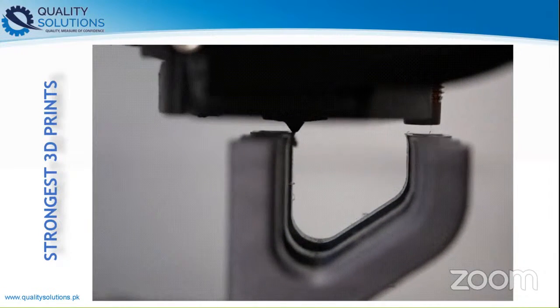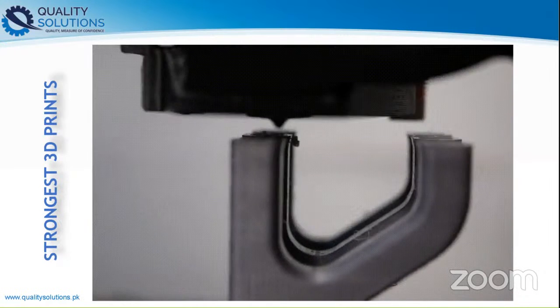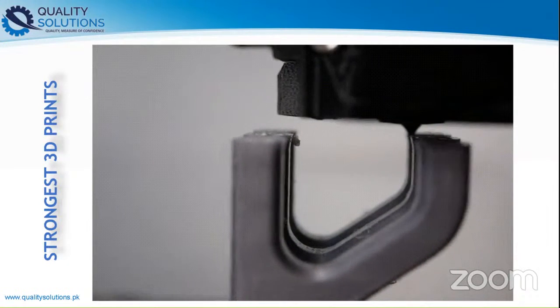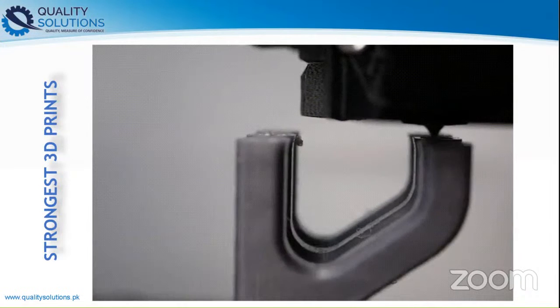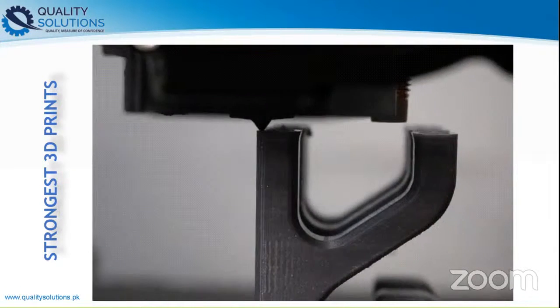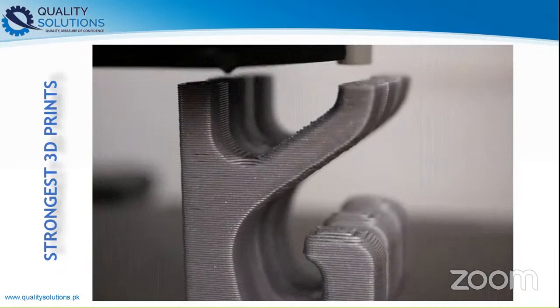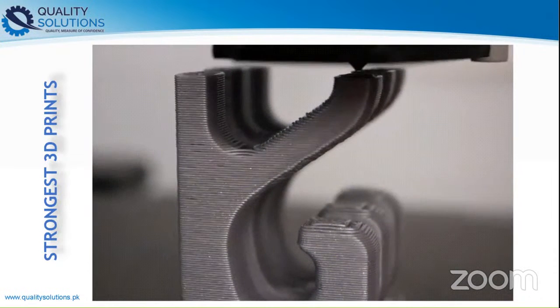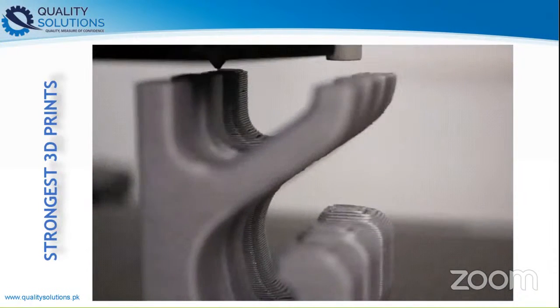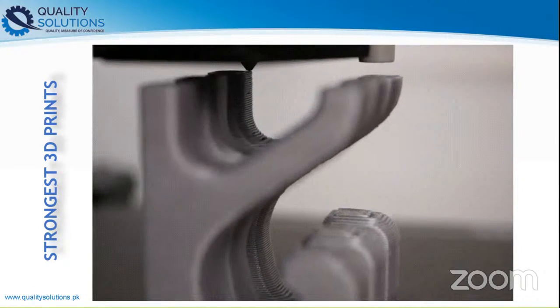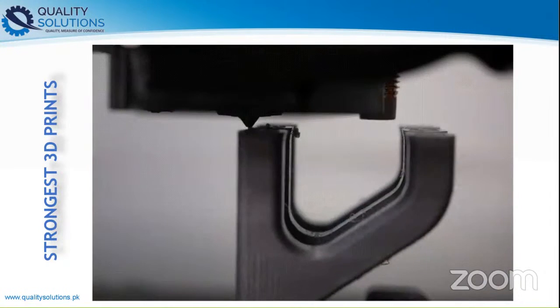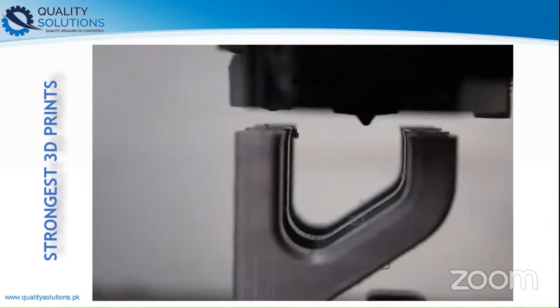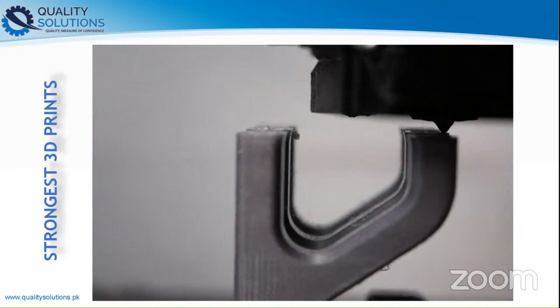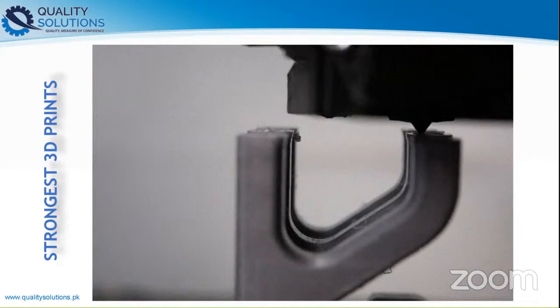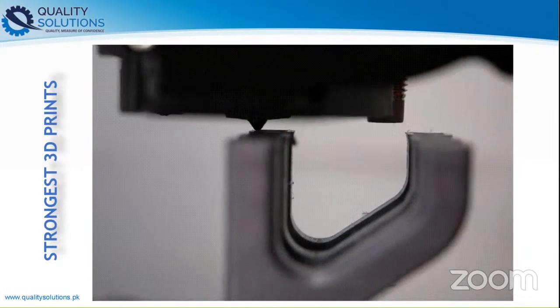What I mean is that, for example, a 5 micrometer tolerance on a thin layer is way worse and could result in plus minus 10% over or under extrusion, whereas the 5 micrometer tolerance on a 250 micrometer layer thickness gives you only plus minus 2%. Then there's the statistical aspect.